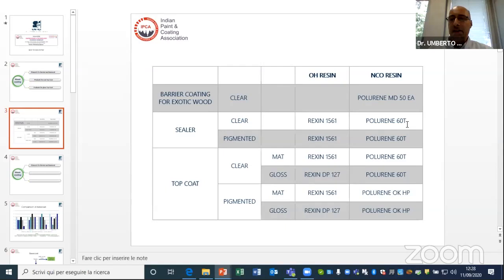The same thing we can say for polyurethane OKHP, with the advantage that, being a hybrid system between TDI and HDI, it allows us to have a better light stability in comparison with polyurethane 60T. So both products have a very good compromise between the fastness of drying and the longer pot life. Very, very good compromise. And both are suitable for matte or gloss systems. So with only 2 hardeners, we can cover all the fields of application that we can have on wood.